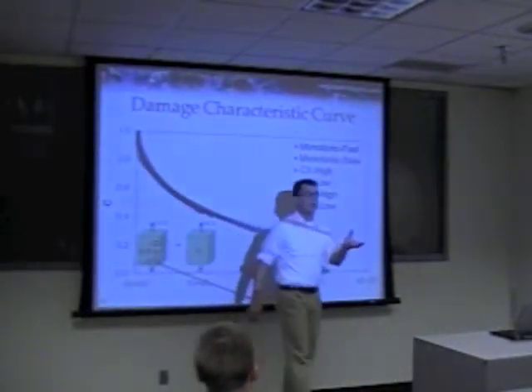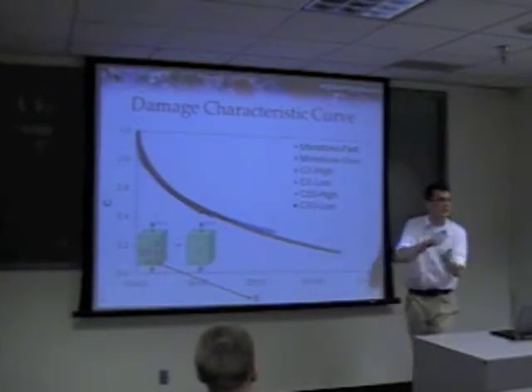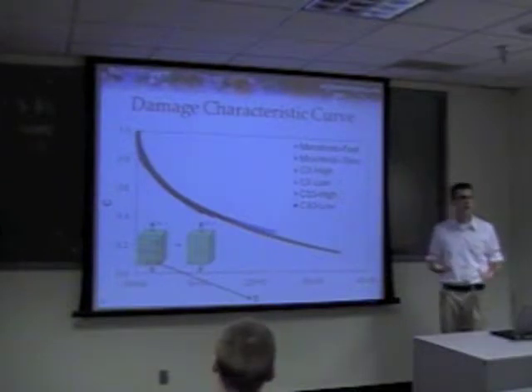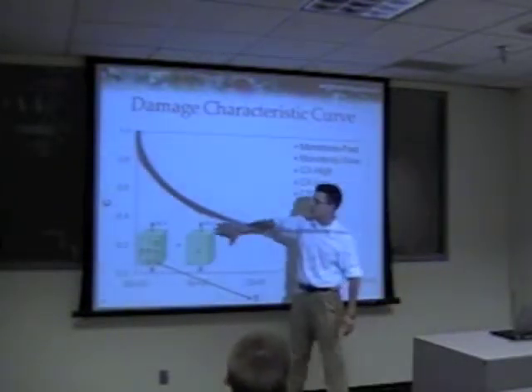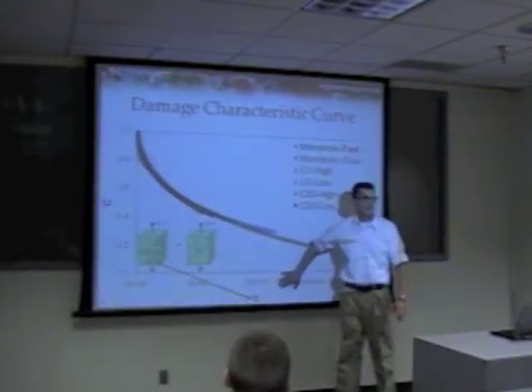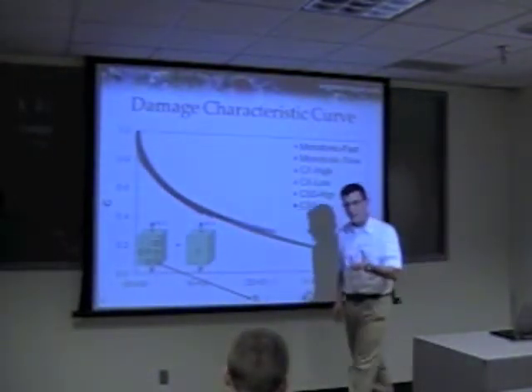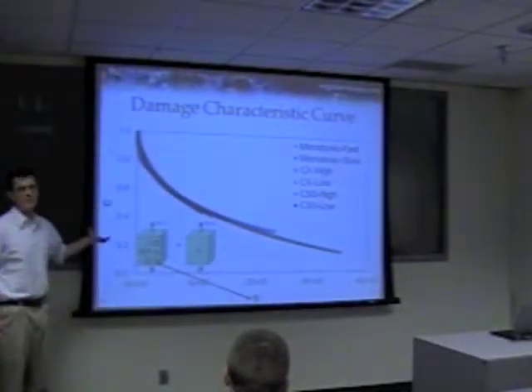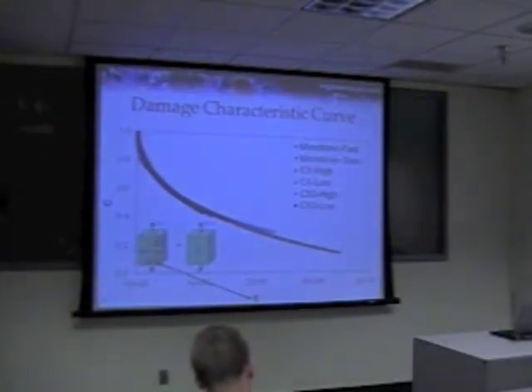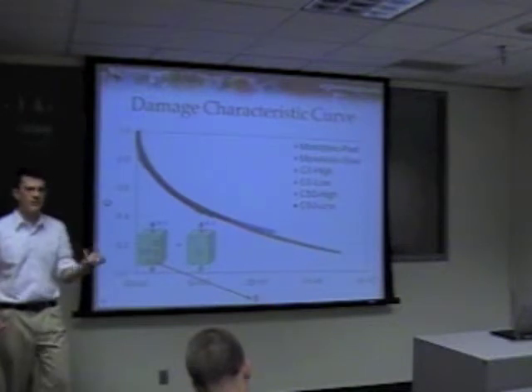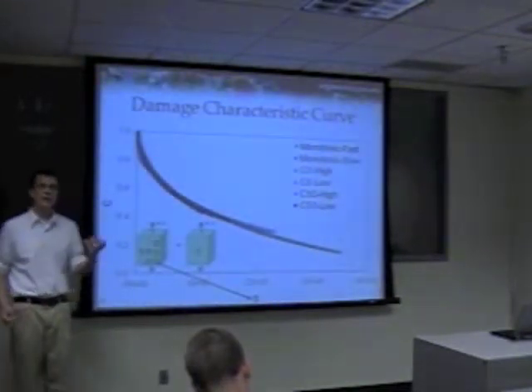It's a very simple concept. As I load the material under fatigue, I create microcracks, which lower the stiffness of my asphalt concrete, and this is the relationship between that stiffness and the damage. It turns out that because we're looking at the fundamental characteristics of the material, this relationship doesn't depend on things like frequency, and it doesn't depend on things like temperature — it's just what the material wants to do.